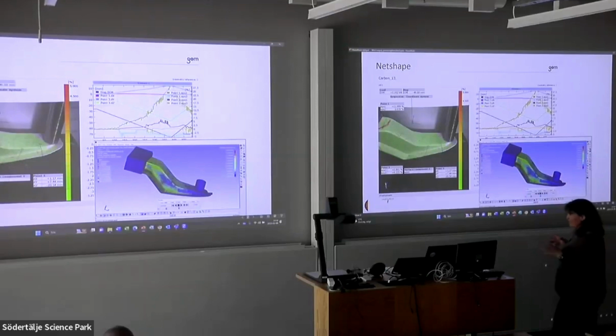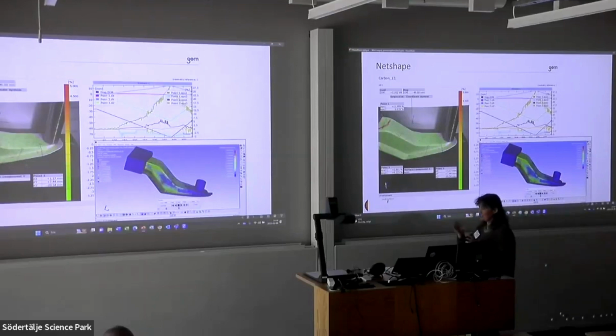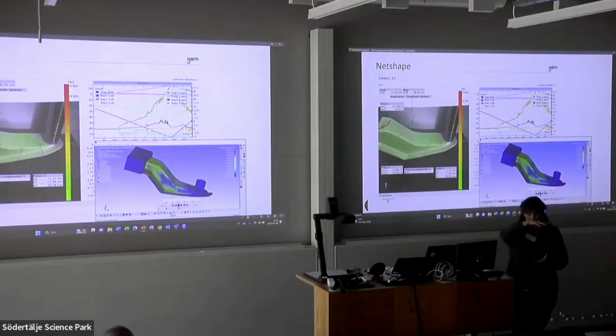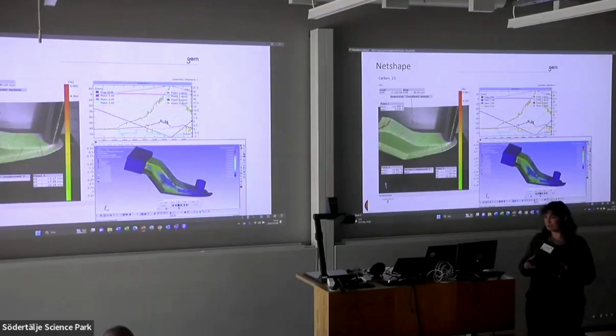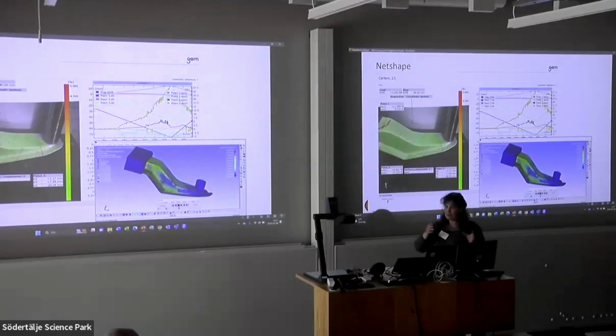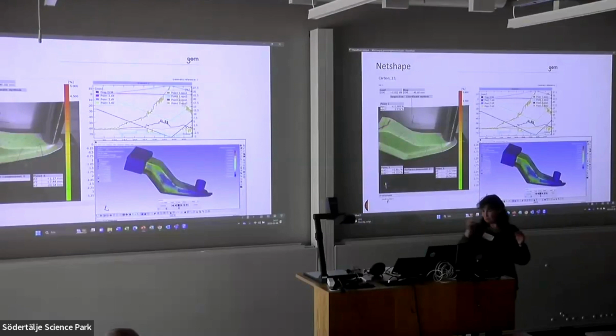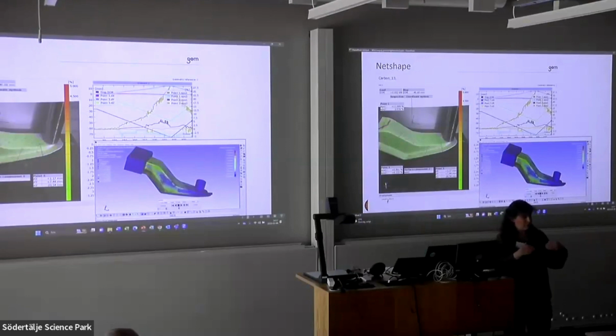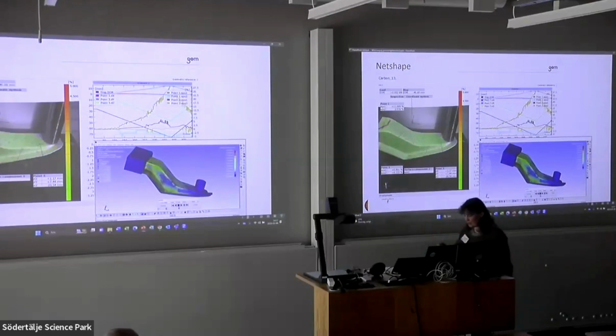What we see is that if we place the charge in different places, in different stacks, in different arrangements, we get different mechanical properties. So if we want to reduce the variation, that stack really has to be controlled. And sometimes it can be a little bit difficult convincing the people who are making it that this actually makes a difference. But it is important that it is lined up. Ideally we used a laser for this, and we stacked it and made the stacks very even. This does have an effect on the properties and on the variation.